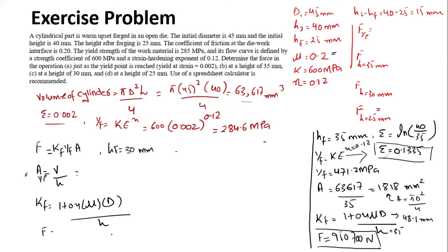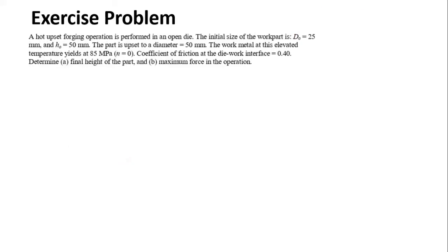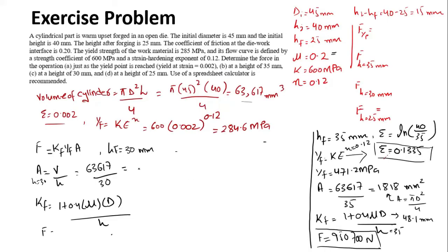So we have the formula, our volume is constant, so the value of the area at h equal to 30 would be 63617 divided by 30. So we have the area equal to 2120.6 millimeter square.